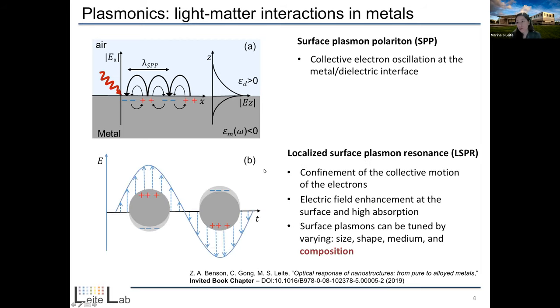So what we can also do if we have, instead of a thin film configuration, a nanostructure, and if again we excite this metallic nanostructure with light at a certain wavelength, we can promote some localized surface plasmon resonance. So now again, here we can have the confinement of these electrons. And that's when we have the situation of this electric field enhancement. So literally, the electric field can increase by several orders of magnitude. And if we can do that, we can actually have a really high light absorption.